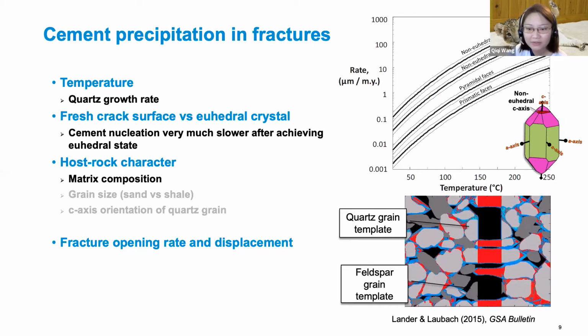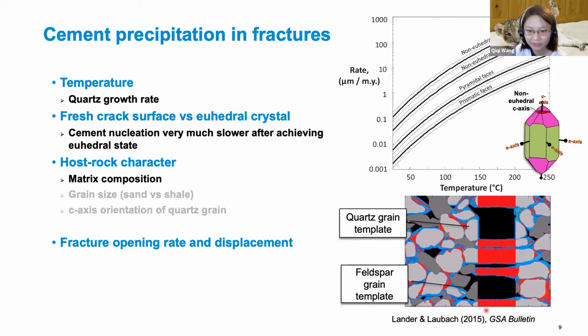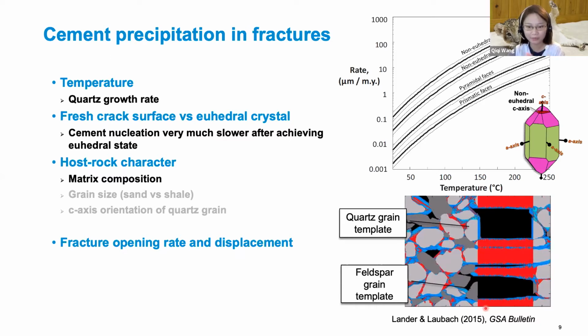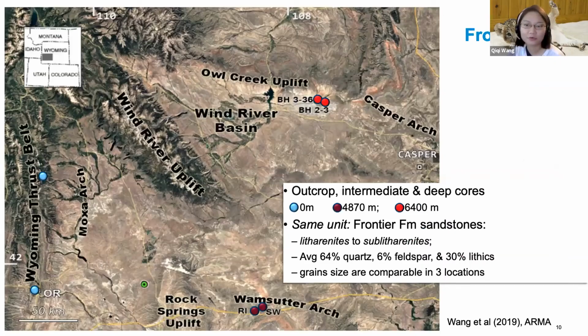Yes. And whether the fracture can be sealed or not also depends on the fracture opening rate. So if a fracture opens fast with large enough displacement, the cement growth cannot keep up with the fracture opening, then we will end up with a lot of pore space within the fracture. Well, all this seems to make theoretical sense, but do we see proof of the theory in naturally fractured sandstones? Now let's look at some real rocks.